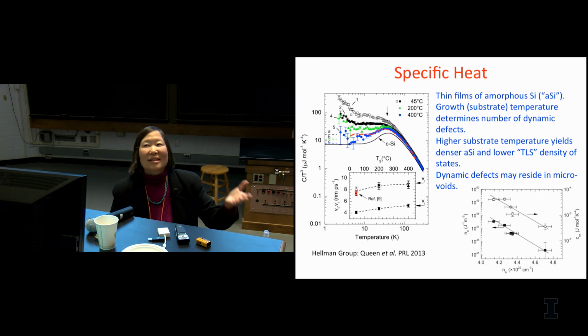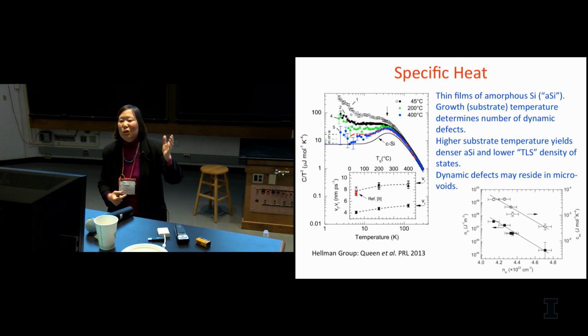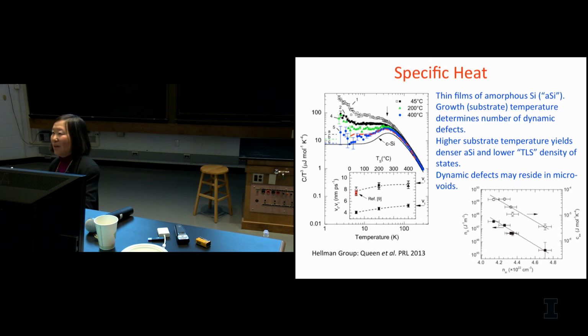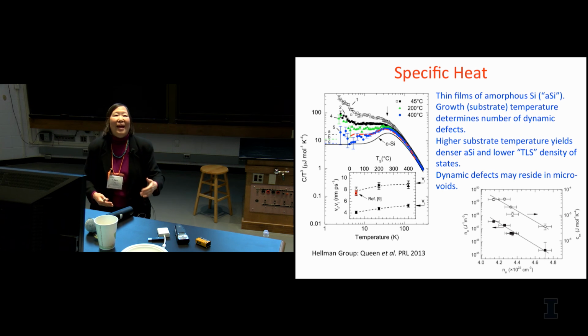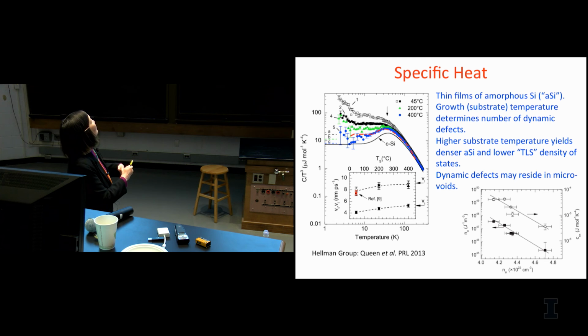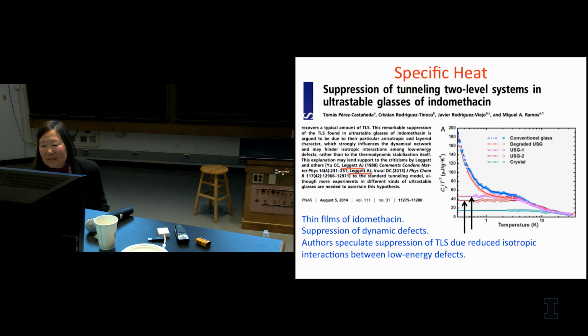And so I think the answer is, okay, so Tony was asking in these materials if you have any cases where you get a linear specific heat, T-squared thermal conductivity, but you don't get the universal value of internal friction, for example. The only thing I can point to is this, and my guess is no, we don't have such an example, because this doesn't look necessarily like, is that linear? Is that going to be linear in temperature? It's too scattered, so it's really hard to tell. If you look at this indomethacin, this looks like it's going to be T cubed, right? So it's flat. So I think the answer is no.